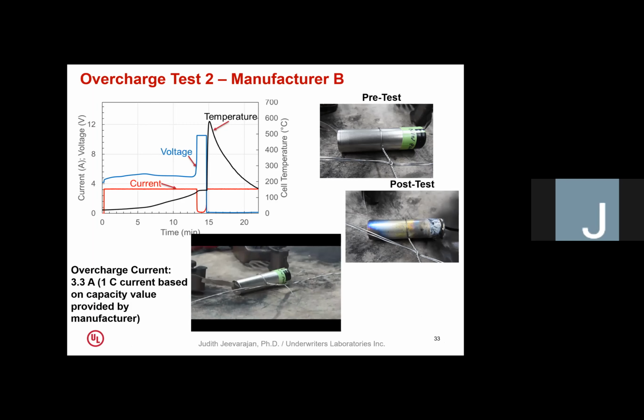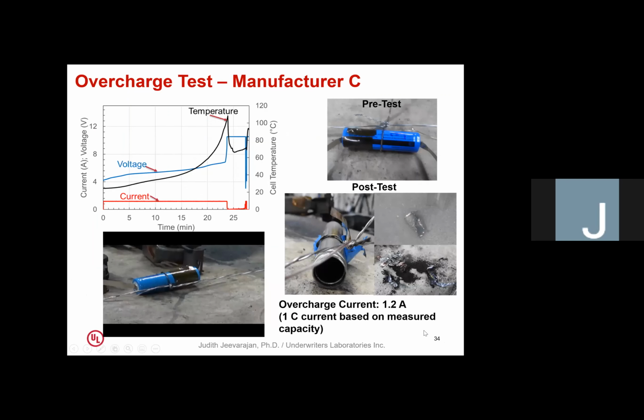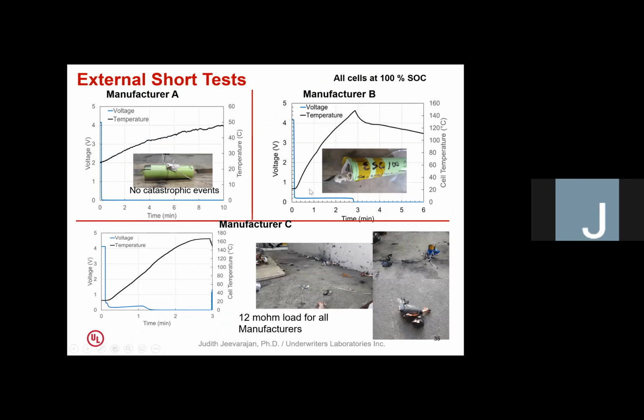So now going to manufacturer C. Here, we did the same thing. We took just 1.2 amp current because we measured only 1.2 amp hour capacity, and we did the overcharge test. And you can see that first the Kapton tape starts peeling, then the shrink wrap or the label on the cell starts peeling. And then we see the cell actually expels its contents, and you can see the shrapnel here on the right side photos. And then we did the external short circuit.